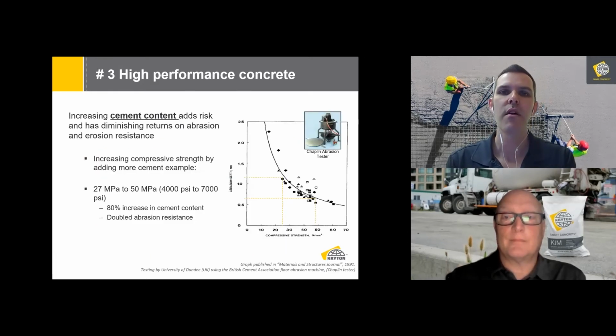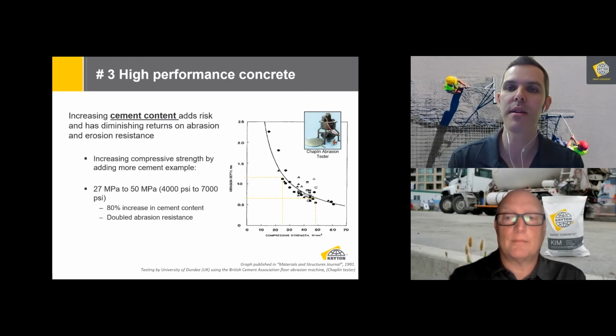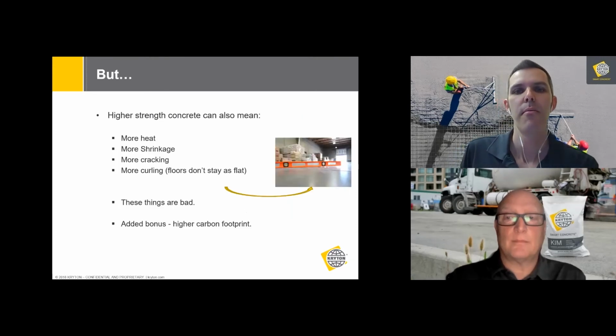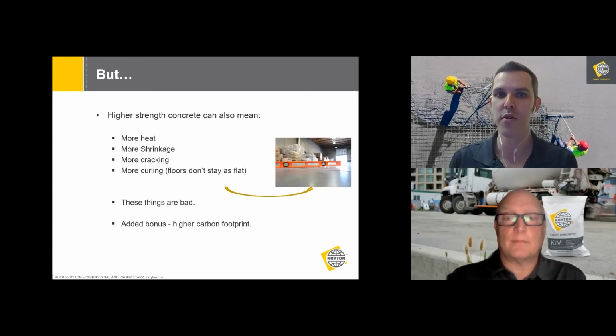Well, the reason is there are some added risks to simply using stronger concrete. Anytime you're adding more paste, you're increasing the amount of hydration, there's more heat, there's more shrinkage. But you can see here, you do get higher strength. Broadly speaking, when you double your strength, you're doubling your abrasion resistance. But for some applications, this will work. For others, it can introduce a lot of unintended consequences that significantly affect the final use of that concrete, especially if you're looking at a floor.